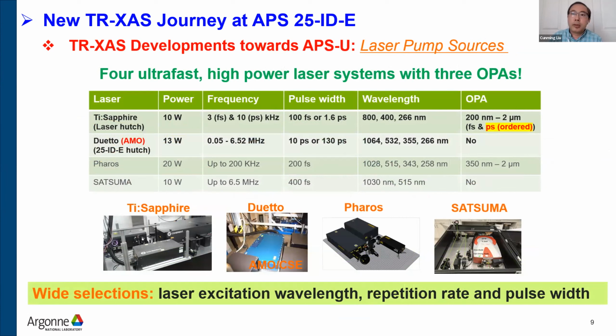This table summarizes the laser pump sources which are available at the new beamline. The Ti-sapphire laser in the laser hutch and the Duetto laser from the AMO group will remain at the new beamline all the time. If users need other lasers, such as Pharos and Satsuma, which are portable, they can be moved from Sector 7 to Sector 25-ID-E for users' experiments. So at this new beamline, we can provide a really wide selection of laser pump sources, covering different laser excitation wavelengths, repetition rates, and pulse durations.